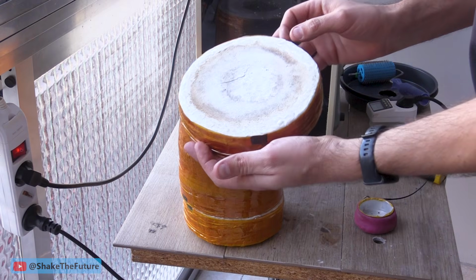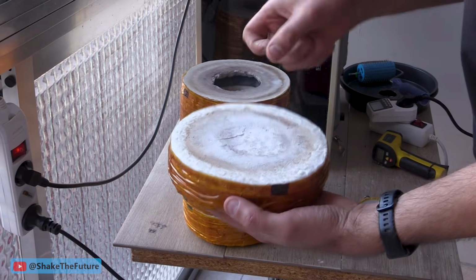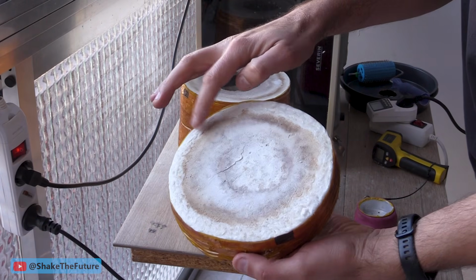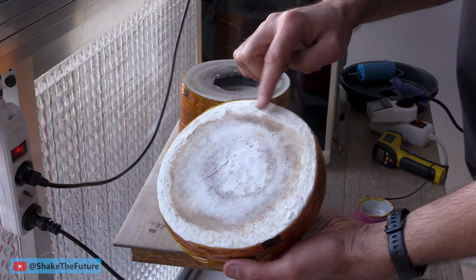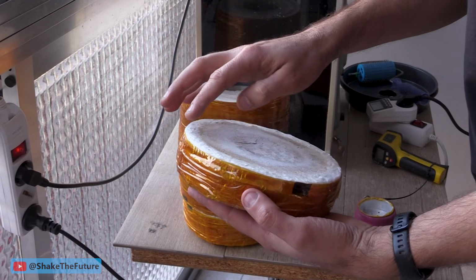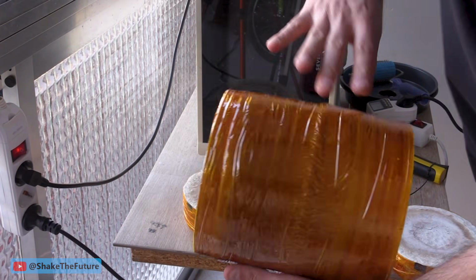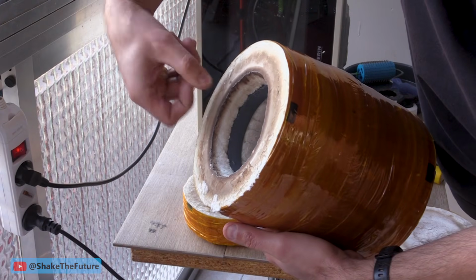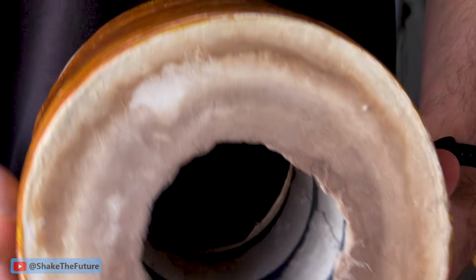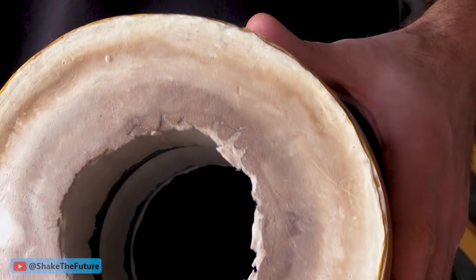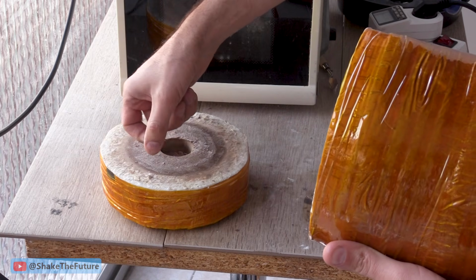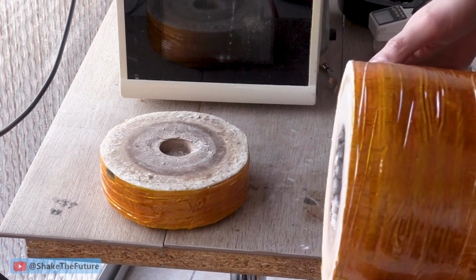And here's the new kiln after around 30 times of use, give or take. Remember that I did not use kiln wash. You can see that some parts of the kiln have become soft. Adding more boric acid would have helped, but only to a point. Rings are in perfect condition. And the base is hard in the center but softish on the sides.